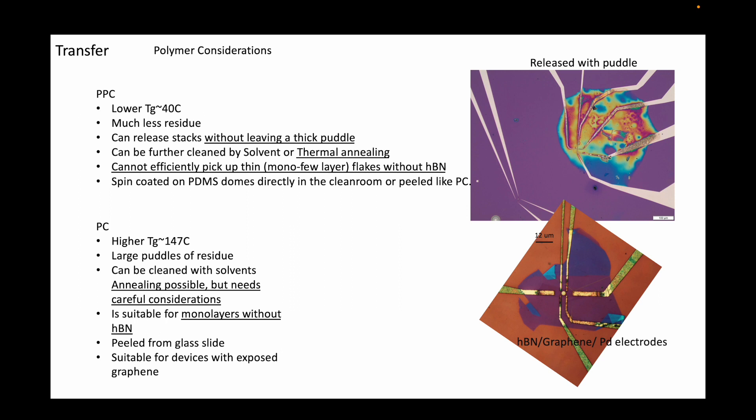PC, similar to PPC, can also be thermally annealed, but requires the presence of oxygen. Therefore, annealing should be performed in air, but the combination of air and high temperatures is usually not suitable for many materials.